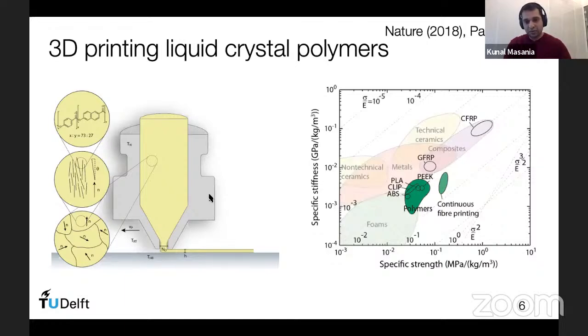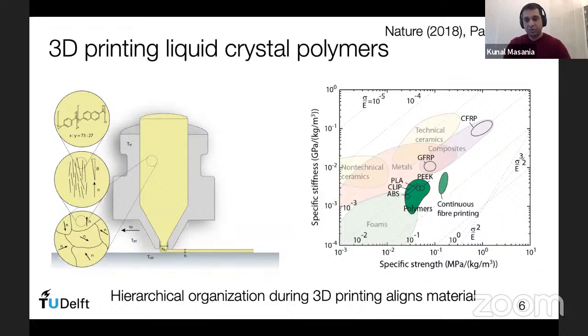And what we were able to do is we were able to take a material which is having similar properties to traditional polymers, and through the hierarchical structure and orientation during 3D printing, we're able to elevate the mechanical properties. So these green dots indicate where we can get to. And so you see here for parts or for lines, we get quite high mechanical properties. And this is quite astounding because it's only a polymer, it's only a plastic, but just by molecular alignment, we can get something which is outperforming glass fiber composites by quite a lot in terms of strength. And it's about 10 times stiffer and 10 times stronger than PEEK as a raw material in the end.